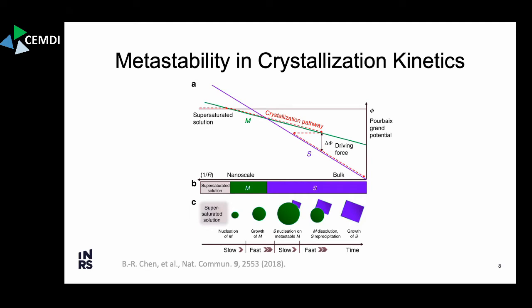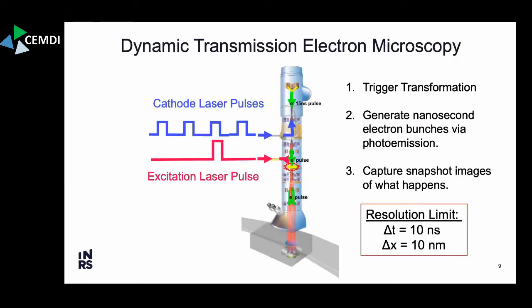So if you look at the end and at the beginning, you might say, well, I don't see this metastable phase, because you have to be able to follow these kinetics. And to answer the question of which metastable polymorphs are really observable out there, we have to get better at following these phase transformations and phase transformation kinetics. So that's pretty much why I'm interested in using the dynamic transmission electron microscope to study these sorts of transformations.